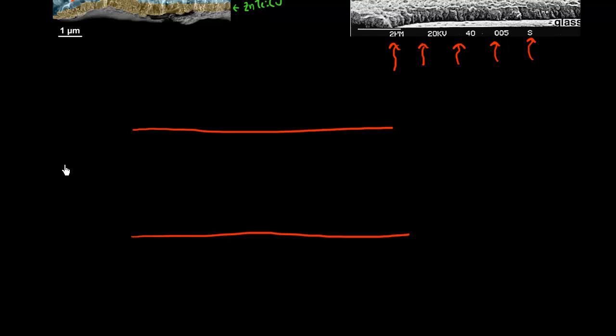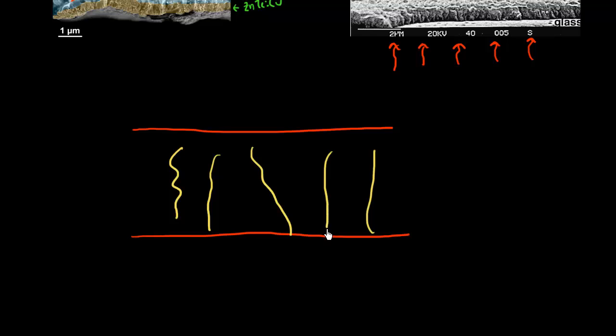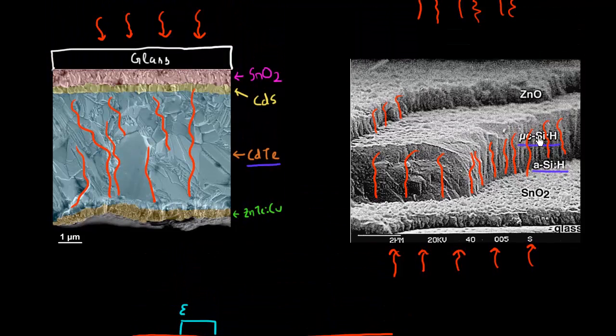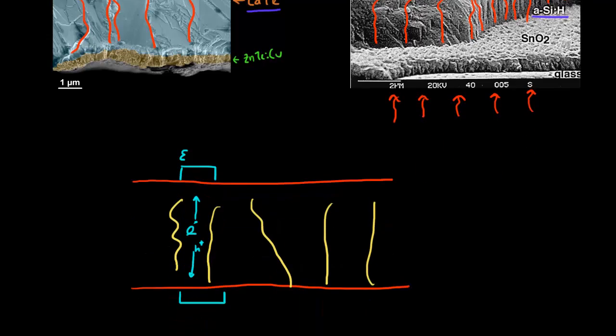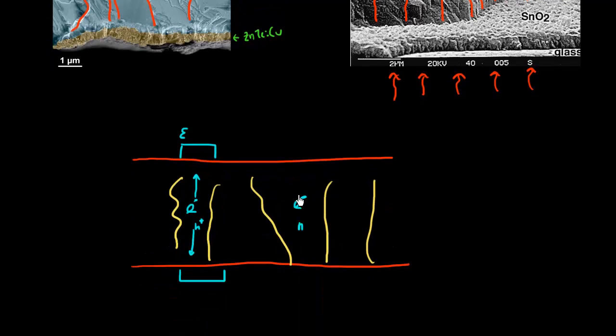Here is what I mean. Assume that this is my thin film based solar cell, and these yellow lines are the grain boundaries running throughout the cell. The electric field is essentially in this direction, with the emitter contact over here, and the electrons and holes are being collected flowing in this particular direction. This direction lies parallel to the direction of most of these grain boundaries. So if an electron-hole pair is generated and collected at this contact, it might not encounter recombination due to the grain boundary at all, because the grain boundary is running parallel to the direction of current flow.